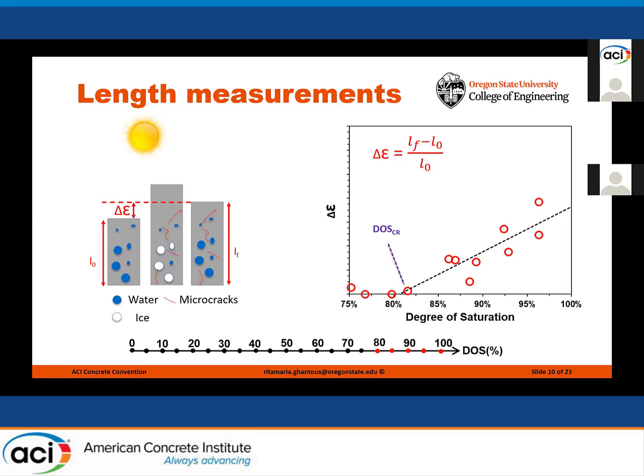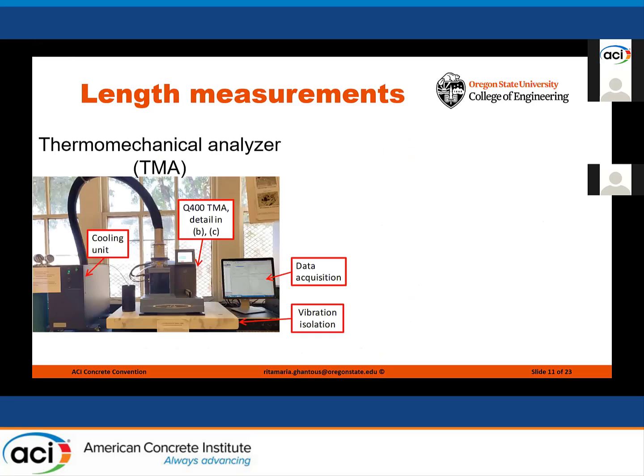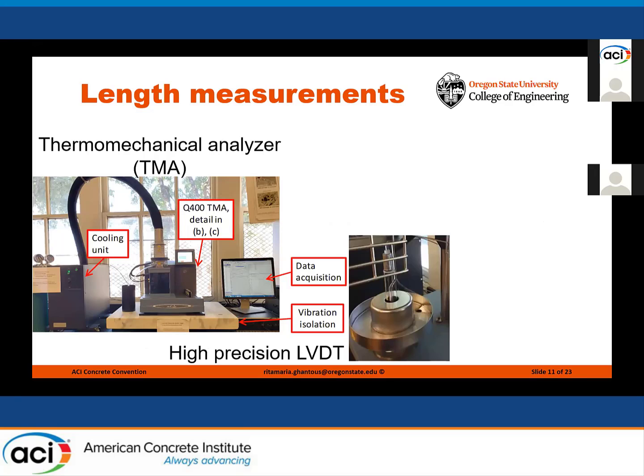To measure these length changes, we use the thermomechanical analyzer. This thermomechanical analyzer will continuously measure the length of the sample while it is exposed to freezing and thawing cycles. This machine has a cooling unit that allows the temperature in the chamber where the sample is sitting to go to negative values. As seen in this picture, the sample is sitting on a stage and the probe is touching its upper surface.